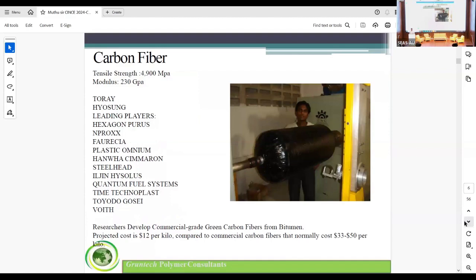So when you choose between Toray or Hyosung, we look at two main properties: not only tensile strength but also modulus. Toray and Hyosung are the leading players. If you start a project next year, you have to book your orders now itself, because the demand is more but supply is less. From Toray, you have to wait 1.5 to 2 years to get at least 1 or 2 tons of carbon fiber minimum. From Hyosung, you can wait 6 to 10 months and get a sizable quantity for prototype making.